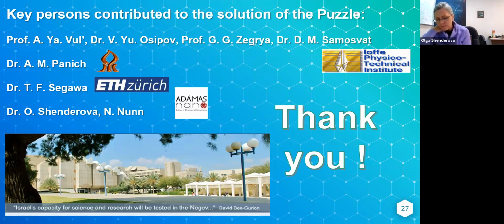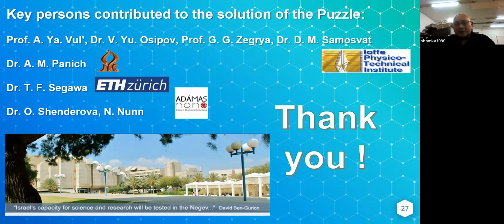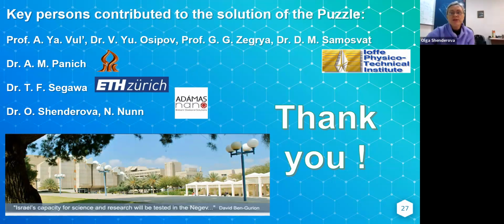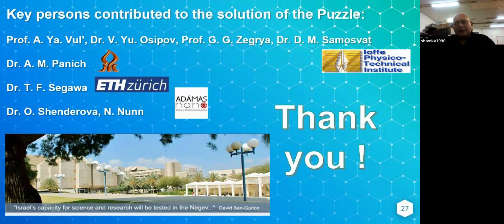Alex, I also have a question. This phenomenon of disappearance of hyperfine structures with nanodiamond size, due to induced interaction with all these multiple dangling bonds, should also be typical for other paramagnetic centers in nanodiamond particles, right? For NV minus, do you see something similar to what you observe for P1? Okay, this is a very good question. Interestingly, it isn't.